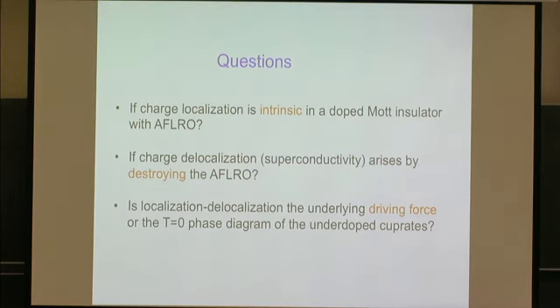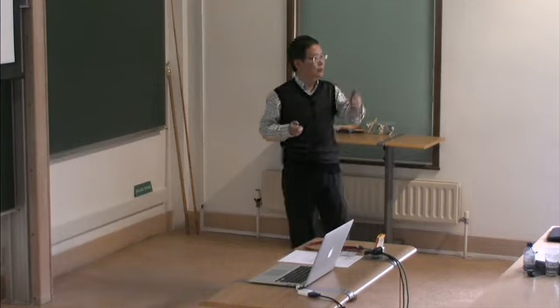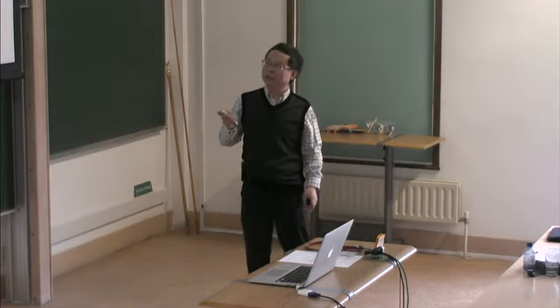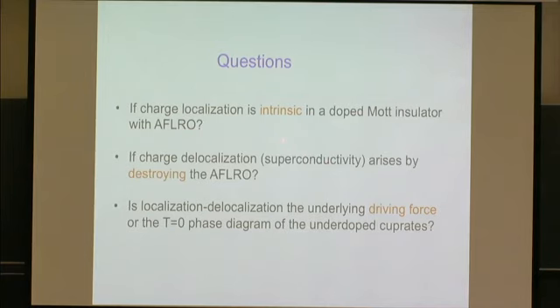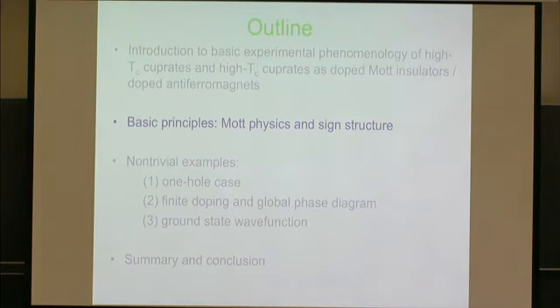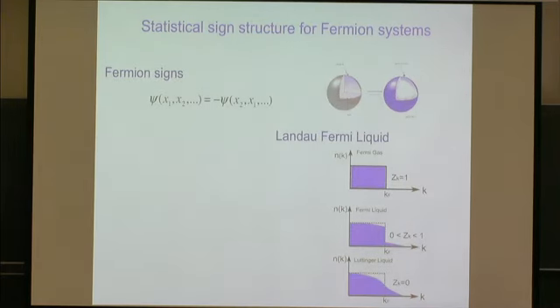So the question would be, is this charge localization due to some Anderson localization because of impurities, or is it intrinsic? If it's intrinsic, then is the charge delocalization, which leads to superconductivity, given by destroying the long-range antiferromagnetic ordering? And if that's true, then the localization-delocalization transition will be the underlying driving force for, at least at zero temperature, underdoped cuprates. To answer these questions, let me come back to some very standard understanding in condensed matter.